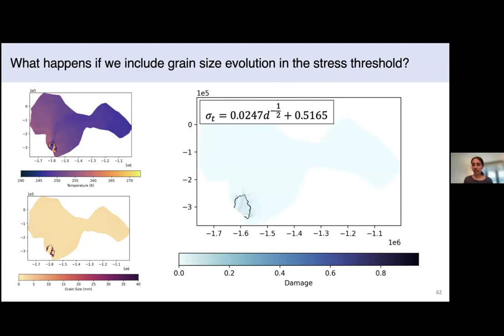Now, notably, what you'll see, this is just our initial damage field, is that there's very little damage. The reason behind that is that we're constraining these damage simulations with this lab-based best fit line. And it has been noted that lab experiments produce larger stress thresholds or larger ice strength values than most observations would show by quite a bit. Lab experiments generally produce somewhere around 500 kilopascals or so, whereas observations are showing more like 90 kilopascals or 200 kilopascals. So there's a bit of a discrepancy here, but because the lab experiments are the best we have to explore this grain size effect, we opted to just go with the lab constrained numbers for now, and then explore more later on.